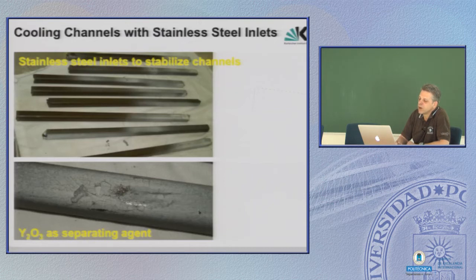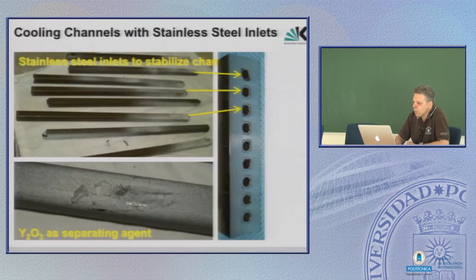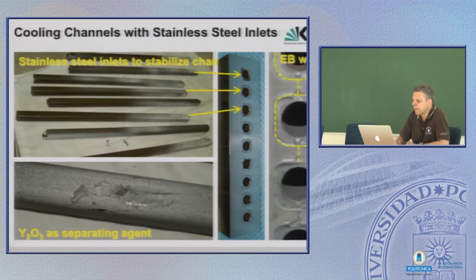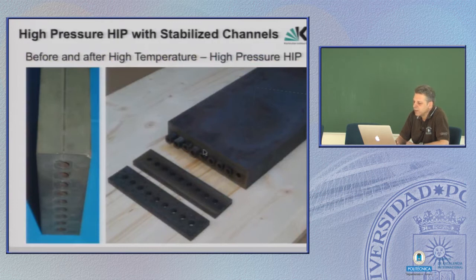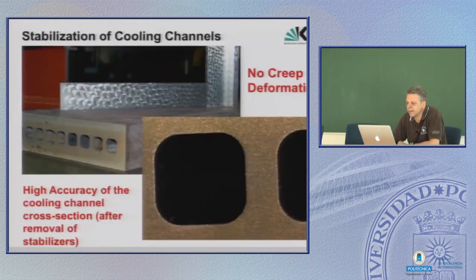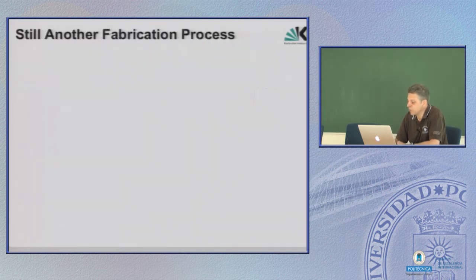So we coated them with a separating agent, put them inside, again welded all these surface lines together in an electron beam welding chamber, and after that, you see here, this is easy to do with an electron beam facility, and then we hipped it, and you see the inlets could easily be removed, and in the end it was a perfect plate. So in principle this could work. We haven't tested it on a real 3 meter long component, but it was a first success to fabricate accurate parts.